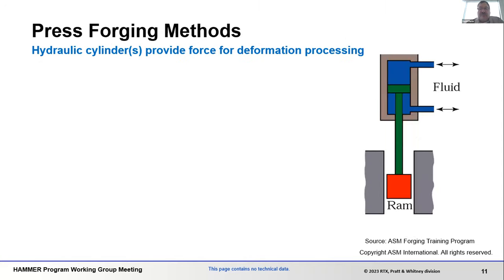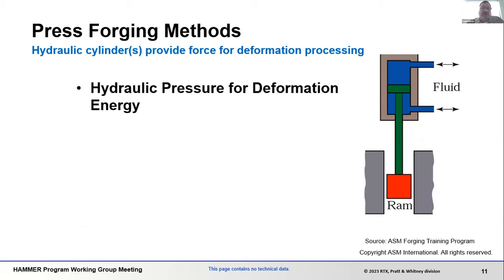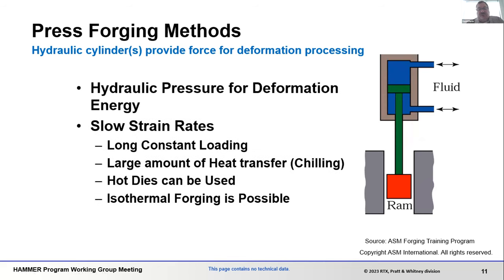So forging press methods, again, you have fluid in a cylinder to force a ram down or up fundamentally. So hydraulic pressure for the deformation energy. Some of the issues with it, it's slow in its strain rate, long constant loading, large amounts of heat transfer or chilling. So that's something that's important for everyone to consider too. Because the deformation processes that you're looking at to make parts, if you're doing them in a heated manner, you have to worry about the temperature distribution. If you're chilling the part in certain areas, but not in others, and in some cases, and I'll talk about it in a moment, if you have very high strain rates, you can have adiabatic heating, and you have to worry about those kind of conditions as well.